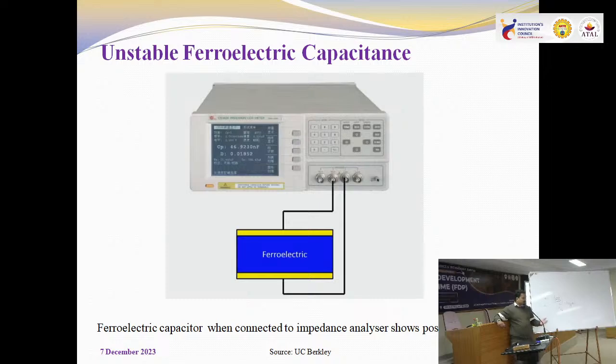When the capacitance is fabricated, it should show, by our logic from the previous slide, a negative capacitance, but it is showing a positive capacitance. How this is happening, we need to understand. Ferroelectric capacitor when connected to an impedance analyzer shows positive capacitance.